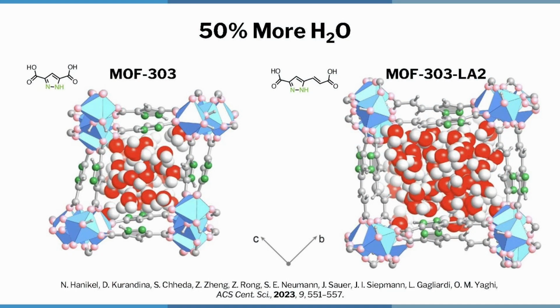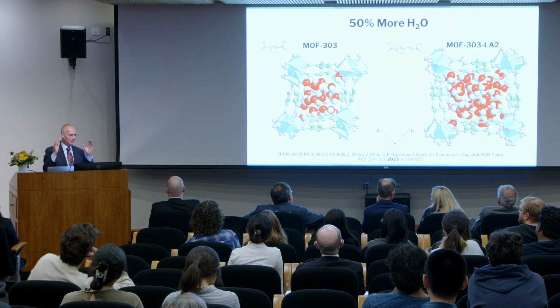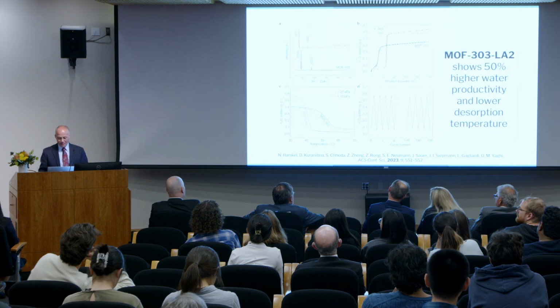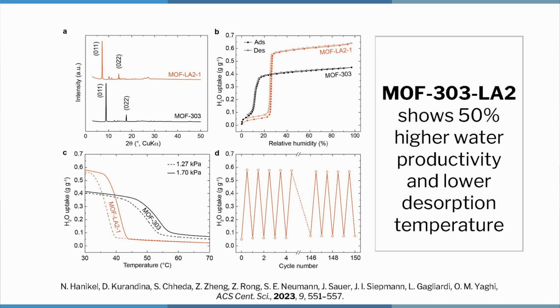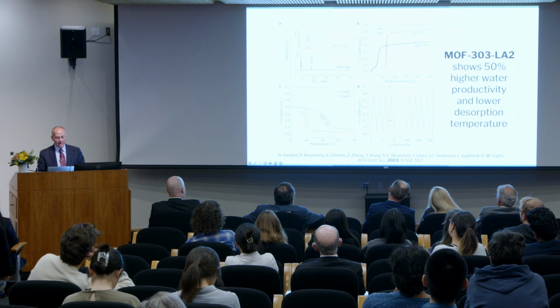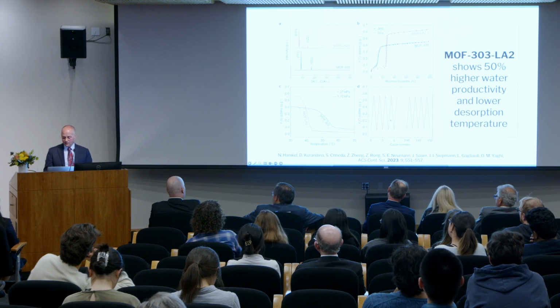So in the end, we surgically inserted 2 carbon atoms into the linker. So this is the original MOF, and now we can, what we call LAX, long arm extension, 2 carbon atoms, and you can get 50% more water in that structure. Same structure, but just a little bit larger. It works in exactly the same way. All the adsorptive sites are exactly the same. Okay, that's what chemistry can do. And you can see here, we're taking up 50% water. The temperature at which you remove the water is even lower than the original MOF, and we can cycle. And this is now a material that's being commercialized in another startup.